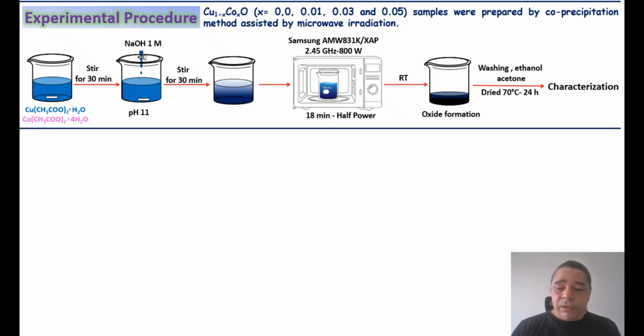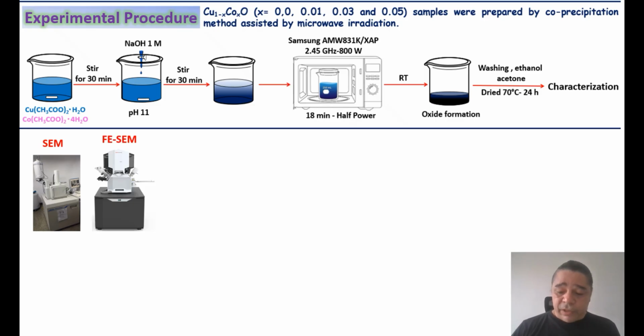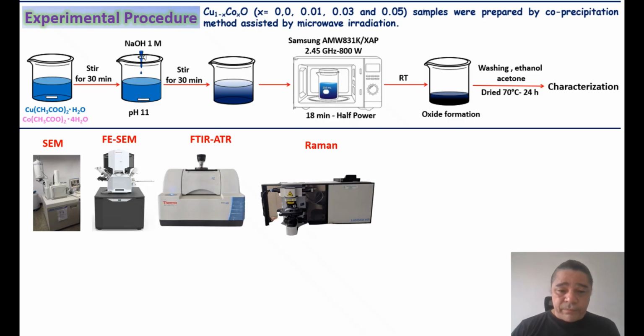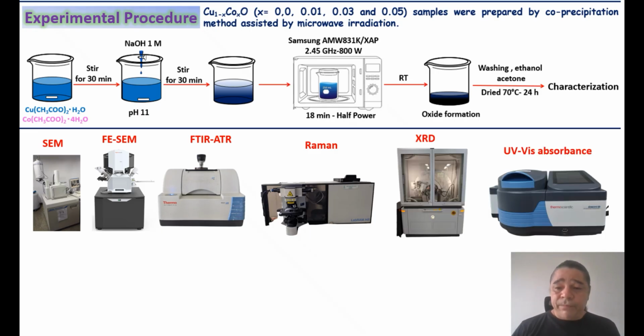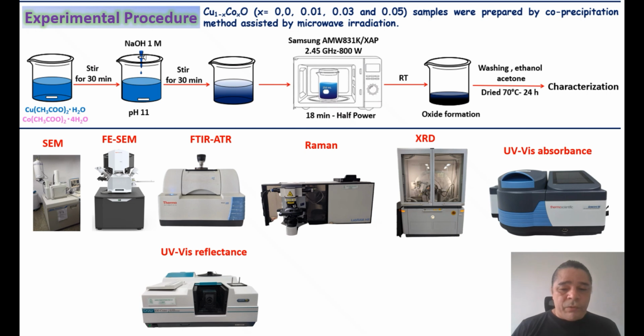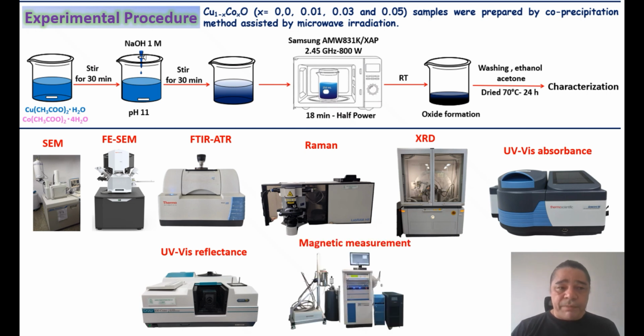The precipitate formed was placed in a domestic microwave oven for 18 minutes using half power. This oxide formed was centrifuged, washed with ethanol and acetone, and dried at 70 Celsius degrees for 24 hours. The samples were characterized by scanning electron microscopy, field emission scanning electron microscopy, FTIR, Raman, XRD, UV-visible absorbance, UV-visible diffuse reflectance, and magnetic measurement.